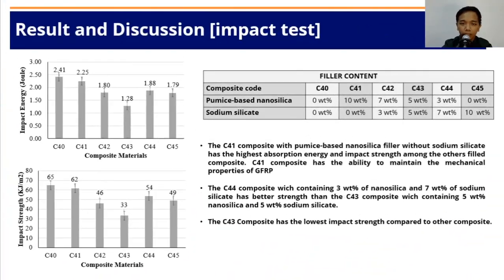The next slide is a result and discussion about an impact test. The chart shown below is the result of the Izod impact testing on GFRP composite. As we can see, from the scope of filled samples, C41 composite, which is only filled with pumice-based nanosilica filler without using sodium silicate, has the highest absorption energy and impact strength among the others.